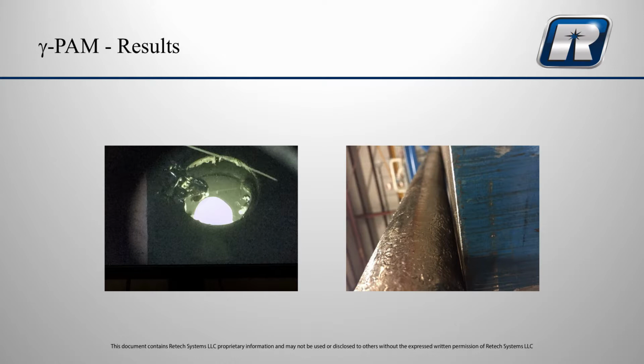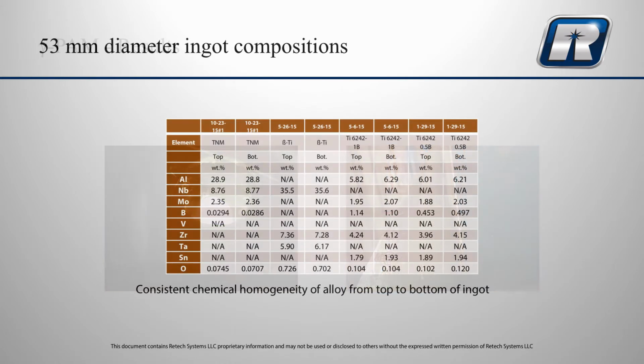But to give you an idea, here's a table of results for various 53 millimeter diameter ingots that we've made. TNM is shown on the very left. That's a titanium niobium aluminide composition with molybdenum, where the niobium is right around 9%, the boron is 300 parts per million, and aluminum is 28.7. I'm very pleased with the chemical results on this. We've also done a beta titanium alloy for a customer here in Europe, looking at a medical application. In this case, they were specifically asking us to introduce oxygen as titanium dioxide into the melt, and they were quite pleased with our chemical analysis results there.